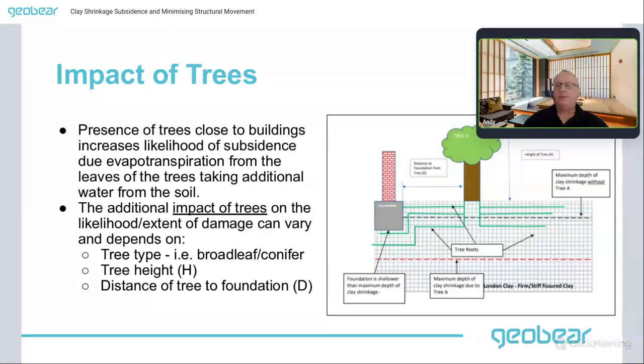There is a proviso there that those guidance stops at about 2.5 meters. So if a large tree is very close to a building, you may find that the depth and height ratio relative to the building is not covered by the design chart. And in those situations, they refer the customer to contact an engineer for guidance. And so in my experience, most of the trees that cause the damage are probably closer than the NHBC guidance covers. So that requires you to do additional investigations to determine the depth of desiccation, as I mentioned previously. I'll be talking more about trees in a minute.